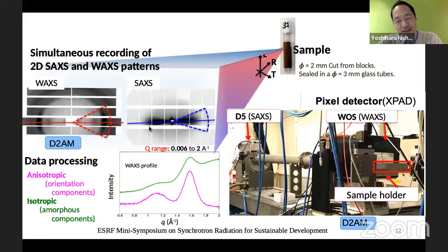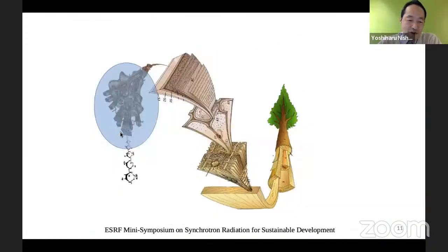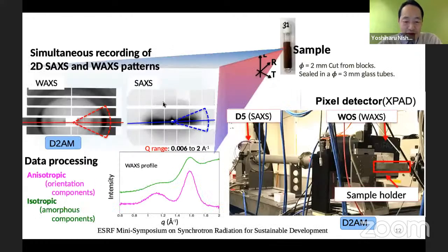This is again very similar work to the first battery example, where we try to look at both the small angle scattering region and the wide angle scattering region to cover both the crystalline region and how those crystals are packed inside the cell wall at nanometer length scale. And here we have an oriented sample, because any wood sample or any plant specimen, when we directly put it into the beam, the structure is in general oriented. So we have this kind of textured pattern. In this case, the fiber axis or the plant long axis is vertical.